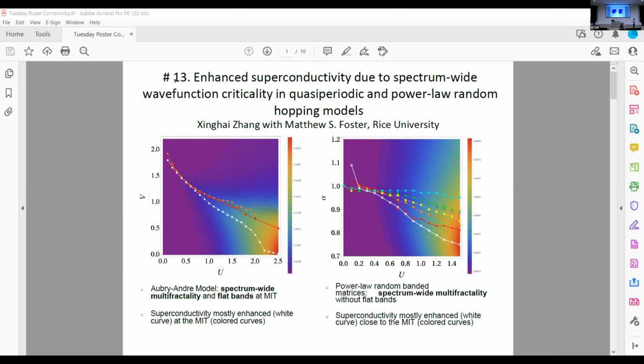Here we show the plot of the order parameter and the phase diagram of the two models. The white curve gives the largest superconductivity order parameter, and the red curve indicates the metal-insulator transition. We can see that the two curves are almost exactly the same for weak interactions, and the similarity of the results in these two models indicates that the superconductivity is indeed enhanced due to the multifractal wave functions. Please come to my poster for further information.